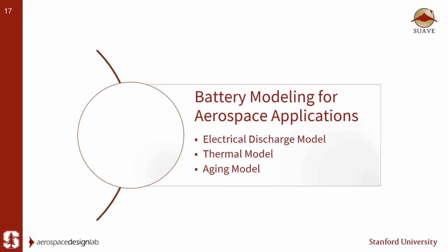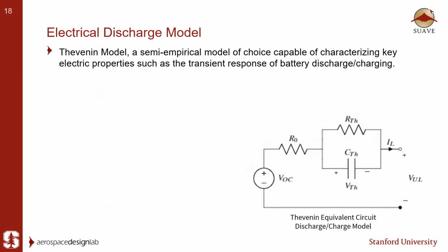So, with that being said, I'm going to shift gears to the second part of my presentation, which focuses on battery modeling for aerospace applications. And in this section, I'm going to cover three main areas: the electrical discharge model I plan to use, the thermal model, and lastly, the aging model. The discharge model chosen for the NCA and NMC chemistries, which I mentioned before, was the Thevenin based model, which is a semi-empirical model that allows for the characterization of not only the steady state, but the transient responses. This is very critical for predicting the battery performance under high frequency load modulation needed to stabilize the aircraft during flight. As shown below, this comprises of four key components: the open circuit voltage, the ohmic resistance, the polarization resistance, which captures the internal resistances, as well as the polarization capacitance that describes and accounts for the transient responses during charging and discharging.